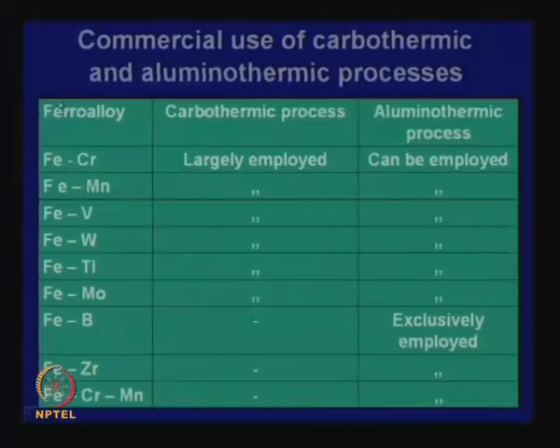Now, let me first talk about the ferroalloys, one or two general things. In theory, and I am again repeating something that I have mentioned many times earlier, in theory, you can reduce any oxide by aluminum or calcium, which form very, very stable oxides, aluminothermic reduction or calciothermic reduction. In theory, all oxides can be reduced by carbon, because as temperature increases, oxides become unstable, but CO becomes very stable. But for carbon reduction, the problem is you may end up not with the metal, but a combination of metal and metal carbide.